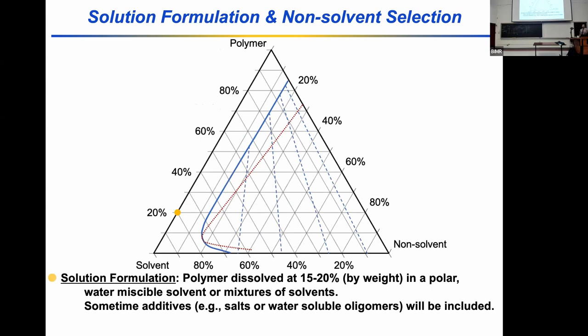And so when we formulate those polymer solutions, we'll often formulate them as pure polymer and pure solvent, so they land on that edge of the triangle, like I stated. They're often about 15 to 20% by weight polymer in solvent.